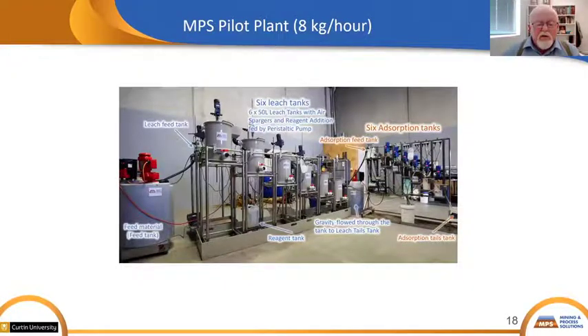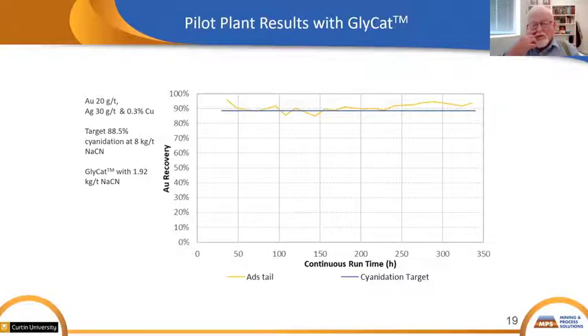Here are some pilot plant results on flotation concentrates. These flotation concentrates assayed at 20 grams per ton gold, 30 grams per ton silver, and 0.3% copper. They were being leached with 8 kilos of cyanide per ton, and the client's stated recovery was 88.5%. Now, the horizontal blue line in the graph is our 88.5%, and the yellow line is the actual recovery that's taken from the carbon adsorption tails.